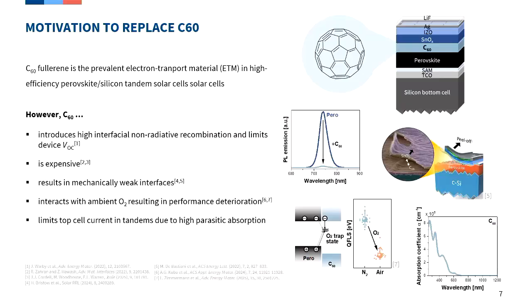It is expensive, at least compared to the ingredients for the perovskite, and it has a couple of other disadvantages. One is mechanical stacking or mechanical integrity is not very high, so the interface with the perovskite with that molecule is very soft.